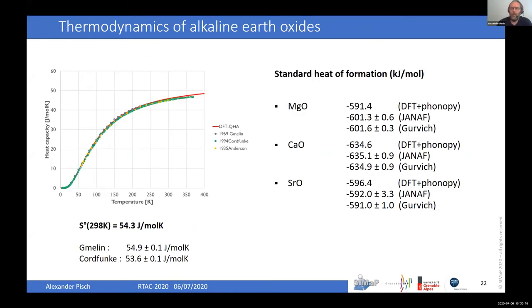Why that? If you look at the standard heat of formation calculated also by the same approach, you see that the value for lime using DFT and phonon calculations is exactly what is measured and compiled in the Janaf and the Gurvich compilations. So there's really an extremely good agreement. The agreement is a little bit less good for magnesium oxide and strontium oxide, where we have errors which are less than 2%, but still it's reasonable.